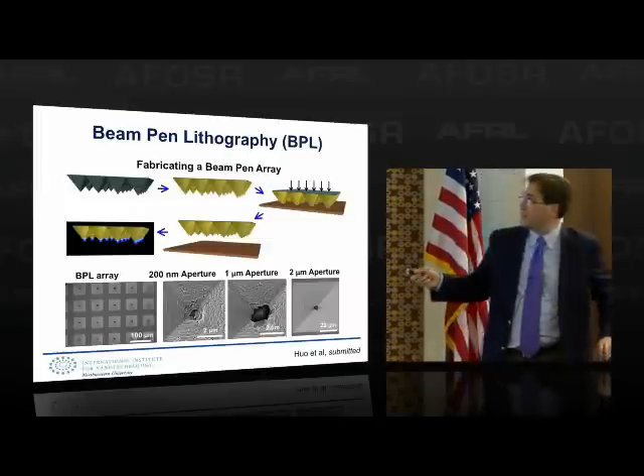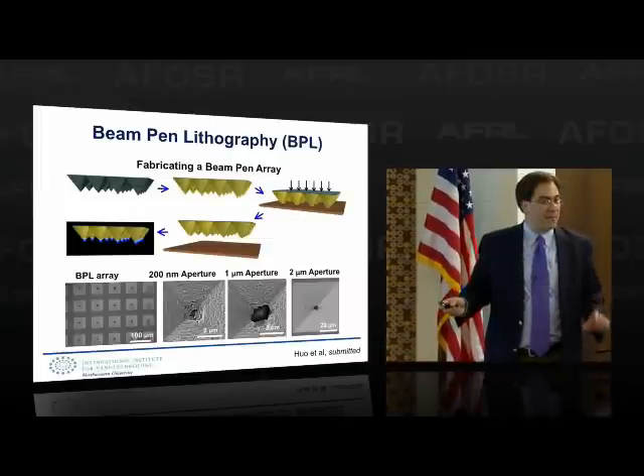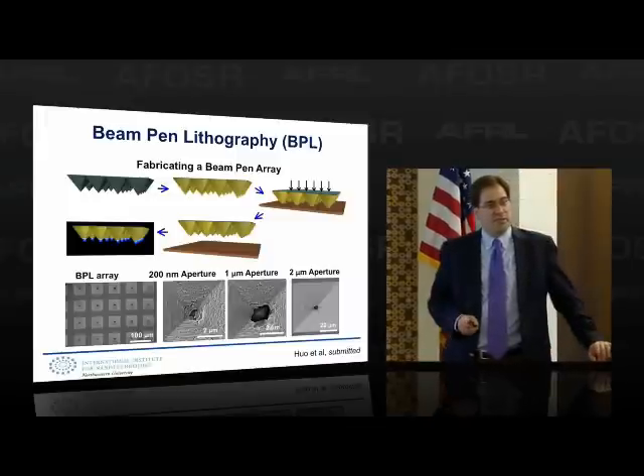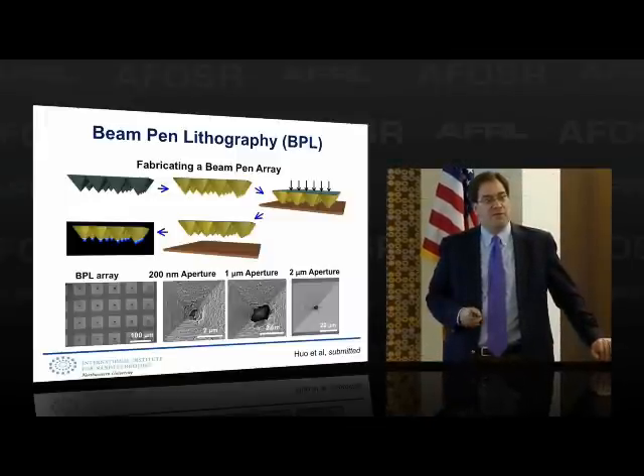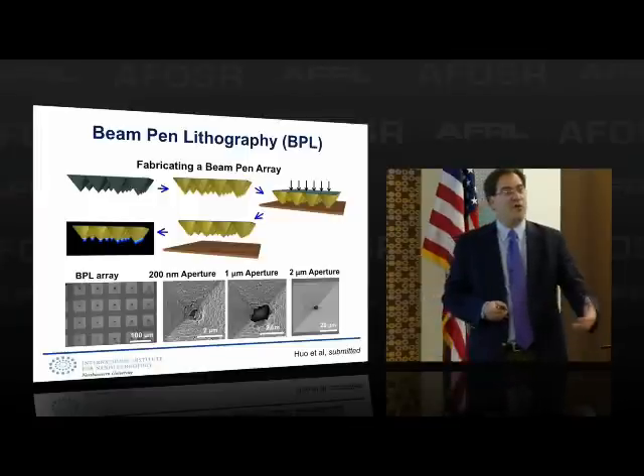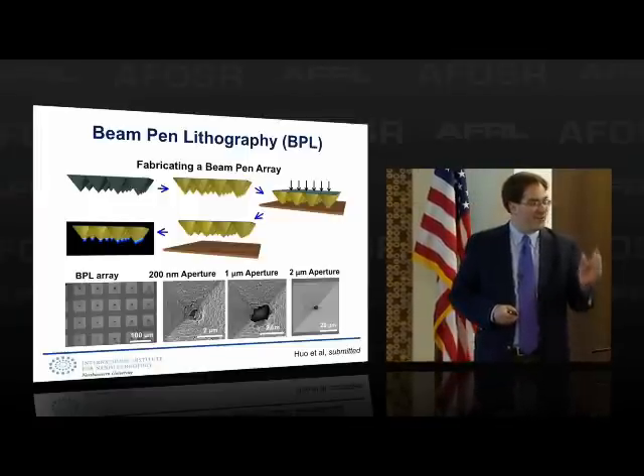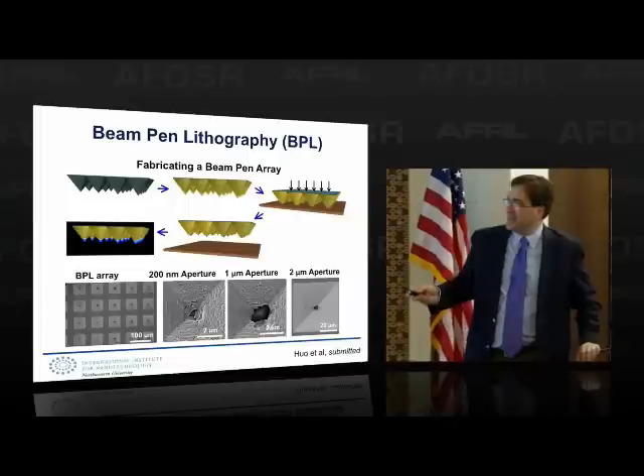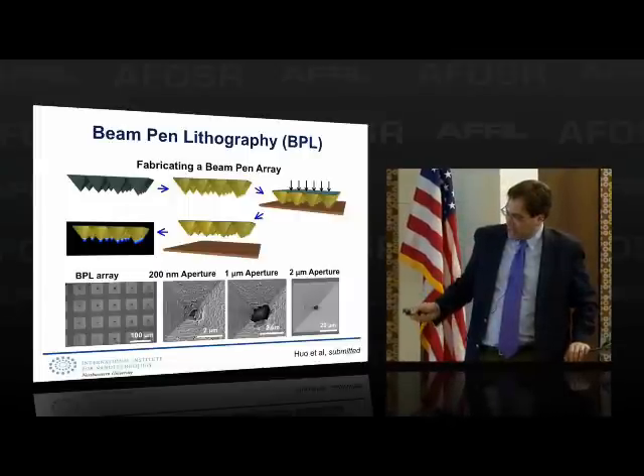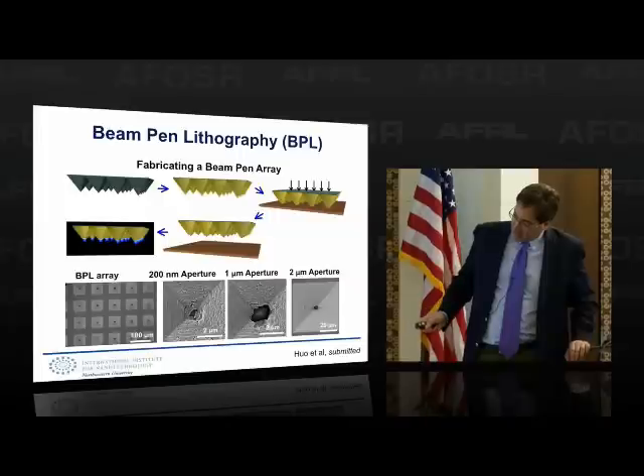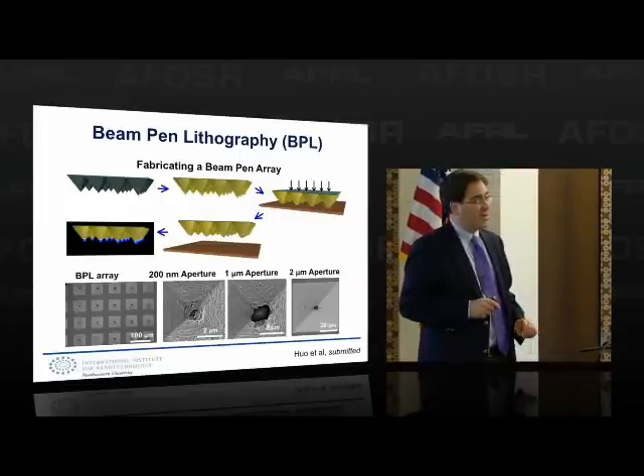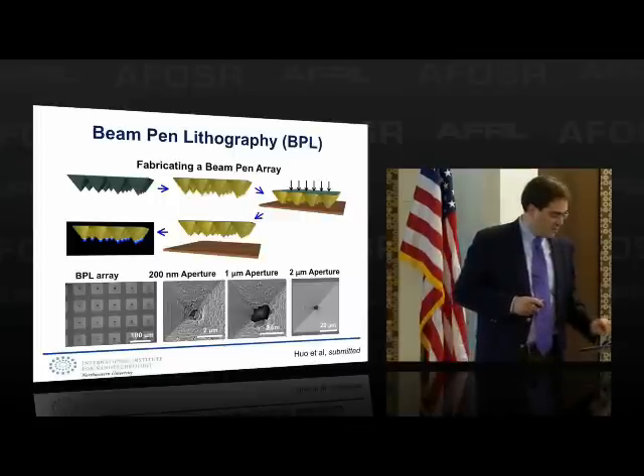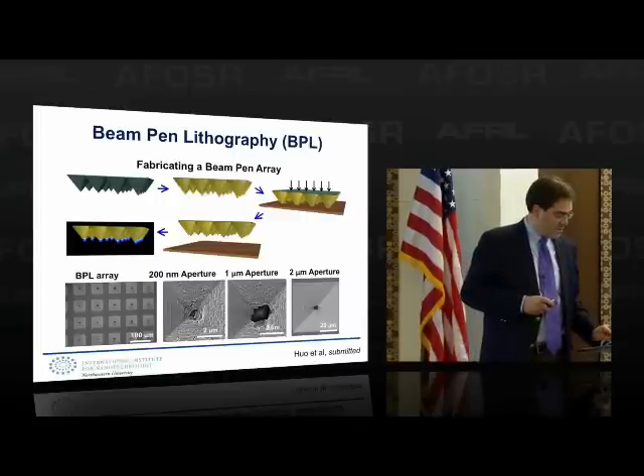channel light delivered from the backside through these tiny apertures. And the beauty of this is I can now work in the near field. And so I can begin to, in principle, use this to develop photoactive substrates underneath with nanometer scale resolution. And so this just shows you some of the apertures that we make, some crudely by the technique I showed here, others where we literally drill holes with ion beams. A lot of this in terms of making it work even better and better is going to be about controlling the size of these apertures.